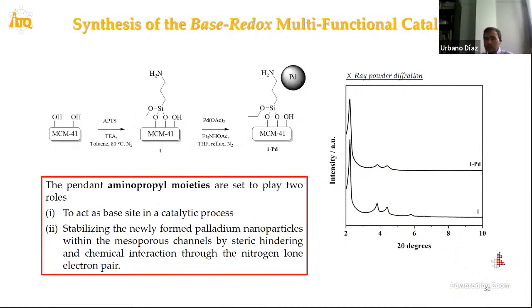It is the case of this type of materials. The hybrid materials previously shown contain amino groups on the surface of the material. It's possible to incorporate additional palladium nanoparticles on the surface, interacting with these external and accessible amino groups. Pendant aminopropyl moieties play two roles, acting as base in a catalytic process and stabilizing the newly formed palladium nanoparticles within the mesoporous channels, avoiding the aggregation of these nanoparticle species.